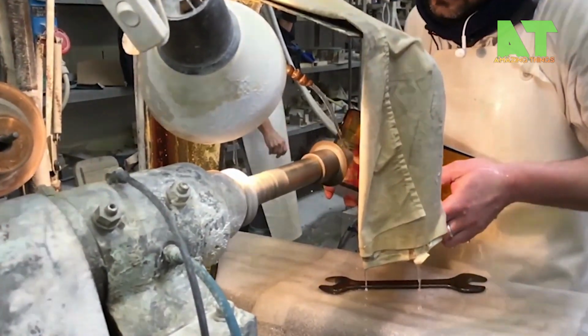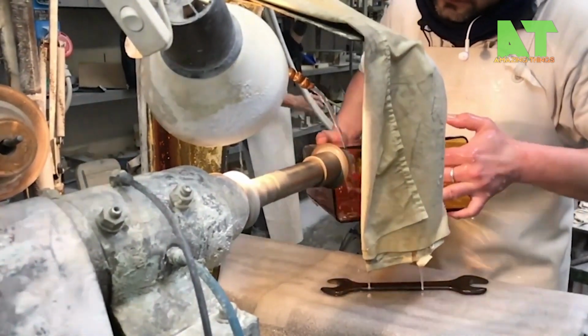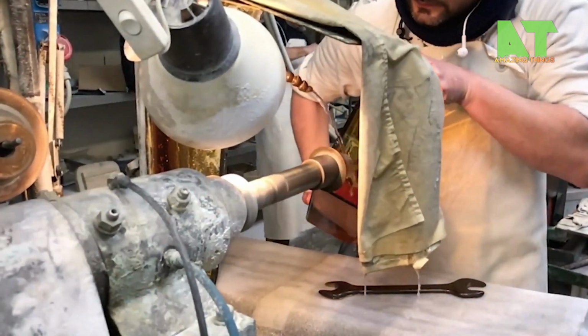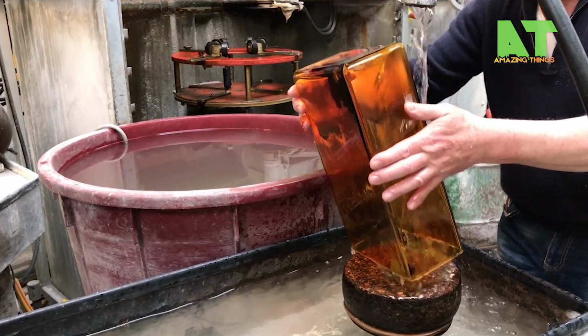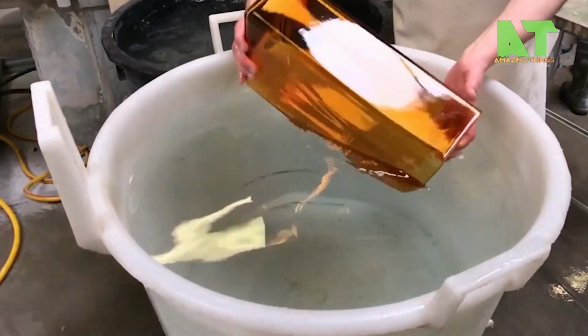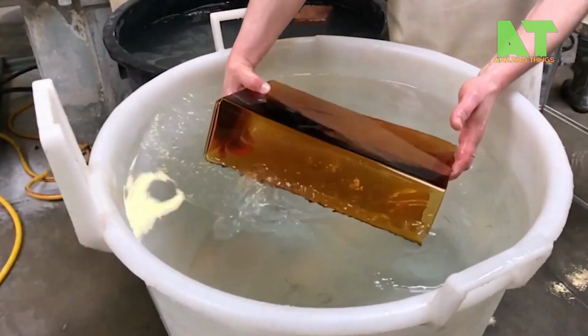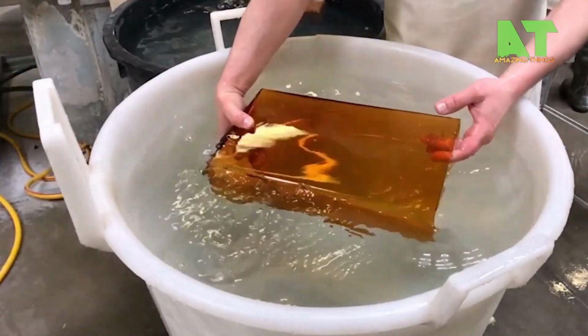That final break-off moment is critical. Done wrong, and hours of work shatters. Finally comes annealing, slow, controlled cooling in a special oven over many hours. This relieves internal stresses that would otherwise cause the piece to spontaneously crack.